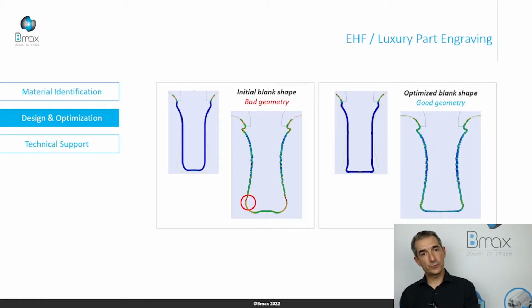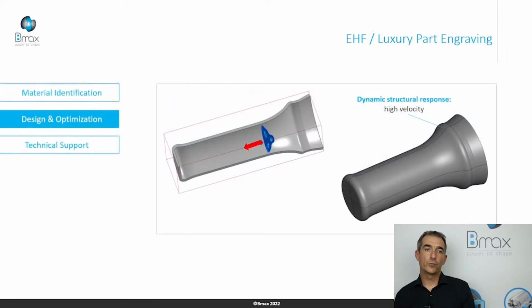And in this way, we reduce the maximum strain, and we fix the crack issue for this process. After, we perform a 3D simulation to validate the whole design, all the components in the system. And we can use this simulation result to analyze what happened during the process. On the left side, it's a pressure wave generated in water into the sample. And on the right, it's the deformation of the sample at the same time.